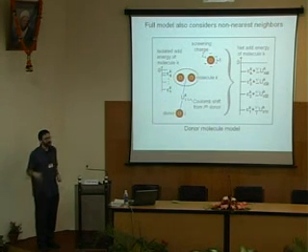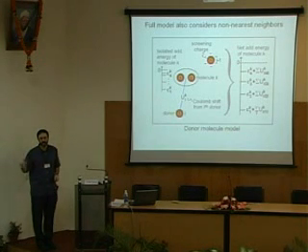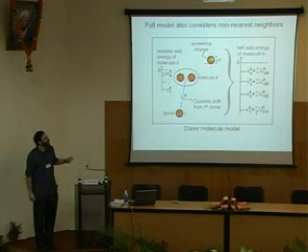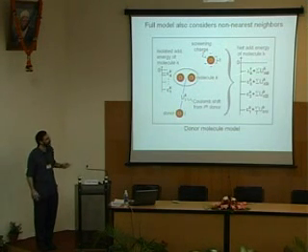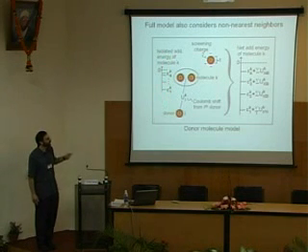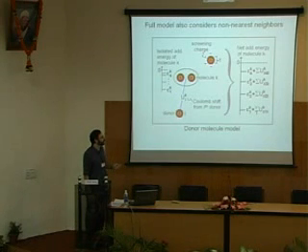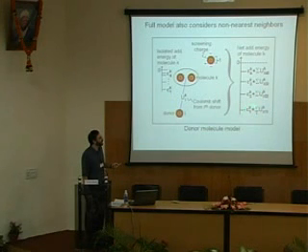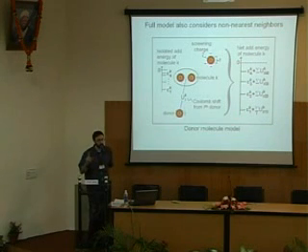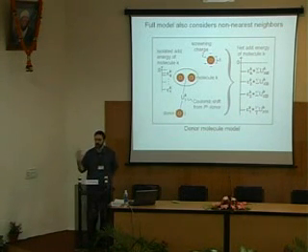That ends up being complicated because as we do the measurement, we're adding charges to the system. The ionization, or the number of charges on these non-nearest neighbors, changes as you do the measurement. So it ends up shifting these boxes up and down in a way that ends up being rather subtle. But we do keep track of that and wrote a nice simulation program to do this statistically. What we'll end up measuring in the end is the average addition energy plus all these shifts from all these other atoms that are a bit farther away. That's shown schematically here. If this doesn't make sense, don't worry, because my cartoon will make sense.